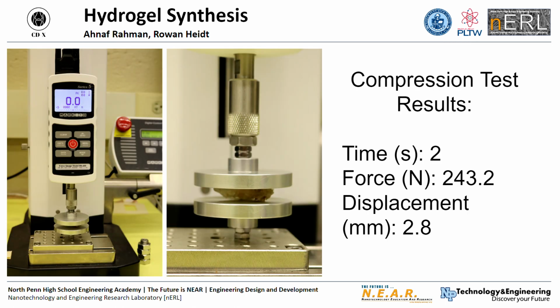Alongside the tensile testing, we also ran a compression test on our sample. And we found that our sample was able to withstand a force of 243.2 newtons when compressed to half of its original thickness, which is about 2.8 millimeters. When compressed further, we found that the measuring gauge we have here on the tester was maxed out and could measure no further without breaking the machine.